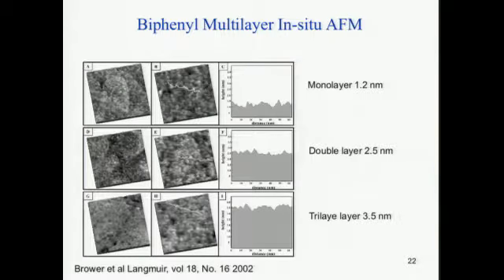And you can also see that the gold terrace kind of disappears, which just means that I'm growing more and more layers on top of the surface. This was done in situ, so we're looking at the same spot over time, and then going back and looking at the thickness. We take our molecules, have them in a liquid cell, pass the molecule that we want to make in the monolayer through, add the connecting atoms, and continue to repeat the process until we get the multi-layer that we're looking for.